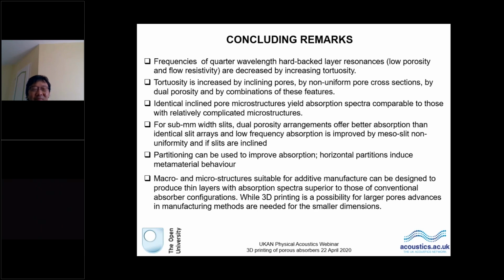So, increasing tortuosity is a way of improving the low frequency absorption of a thin layer, because essentially what you're doing is, in the same way as Philippe was describing, you're slowing down the sound speed within the material so it effectively becomes thicker. You can increase the tortuosity in several different ways. You can incline the pores, you can make them non-uniform, you can intersect them, and you can use combinations of all these things.